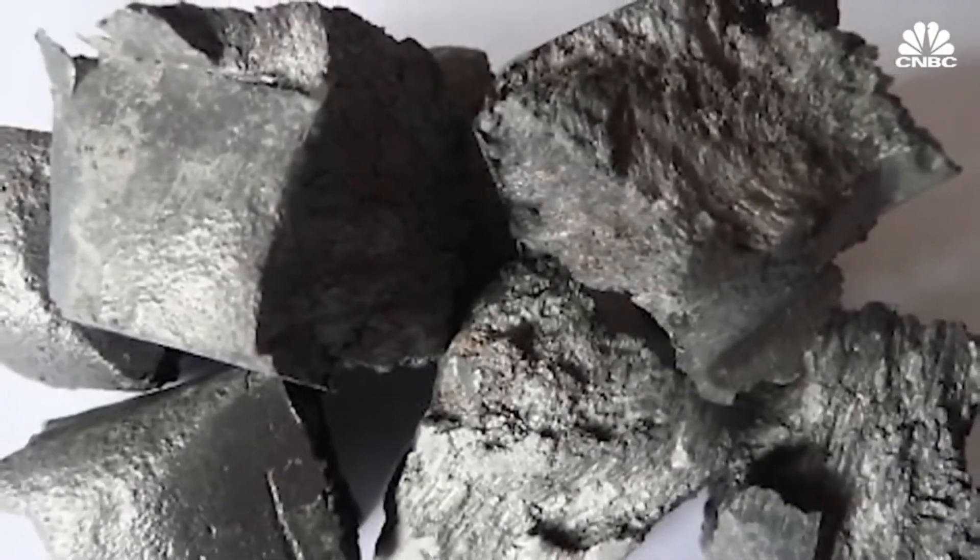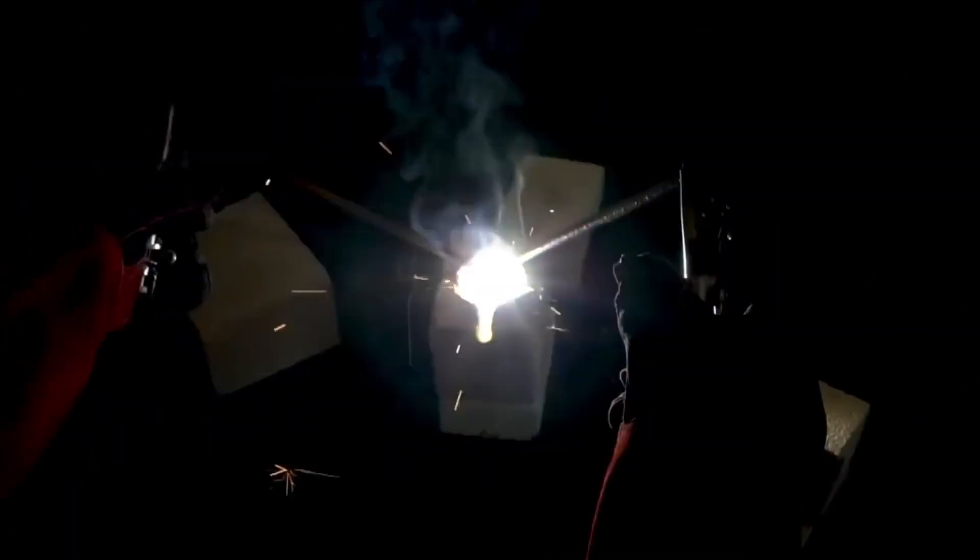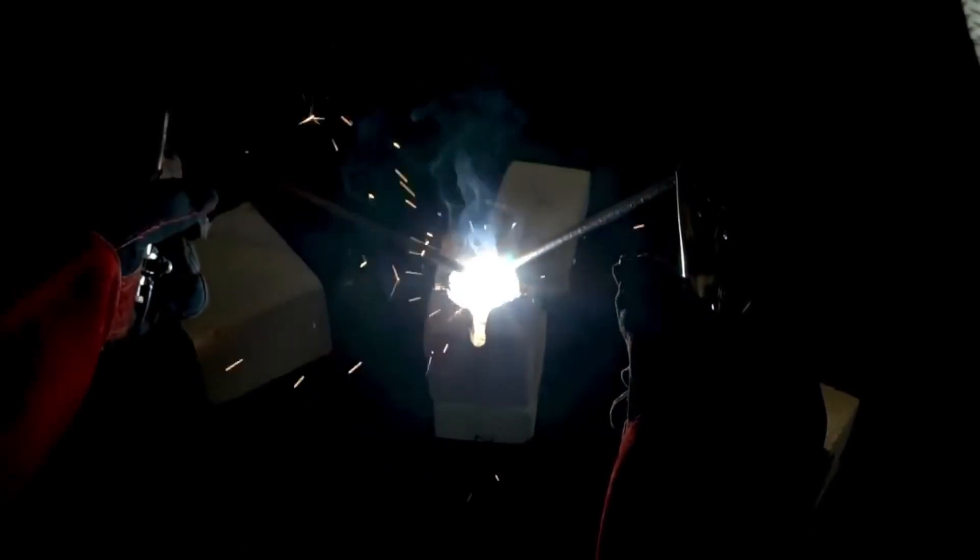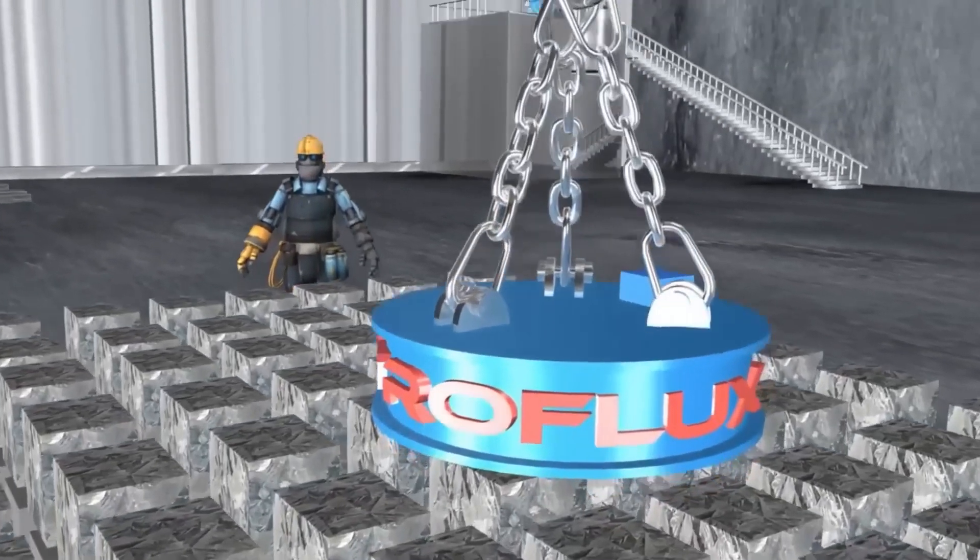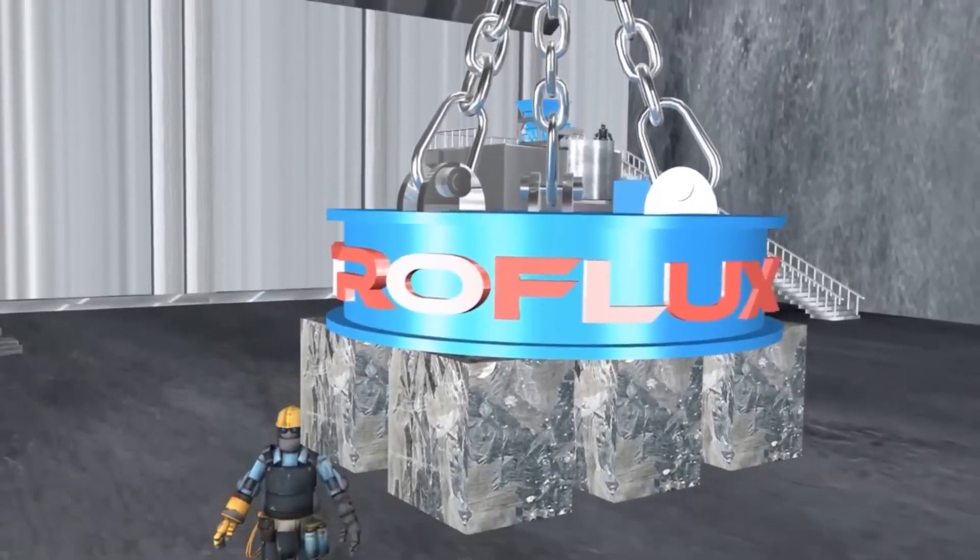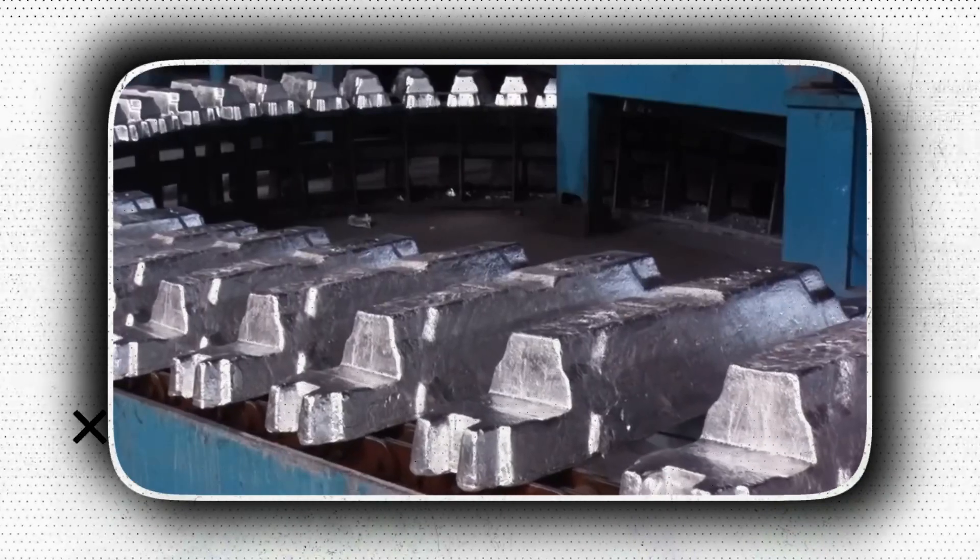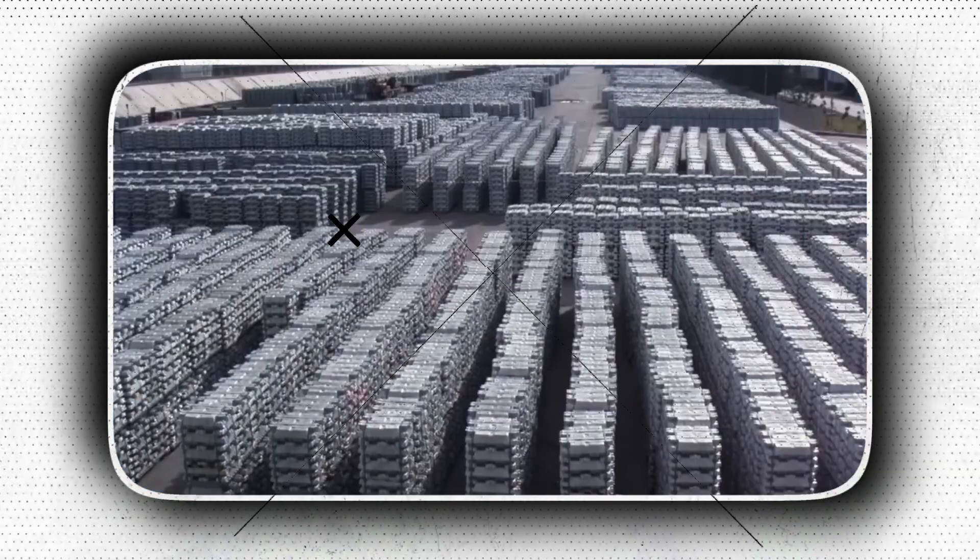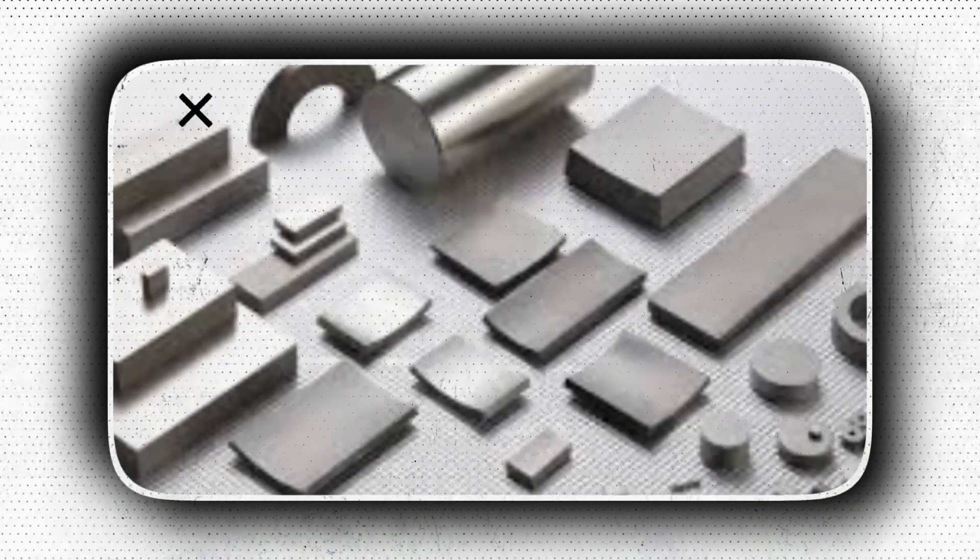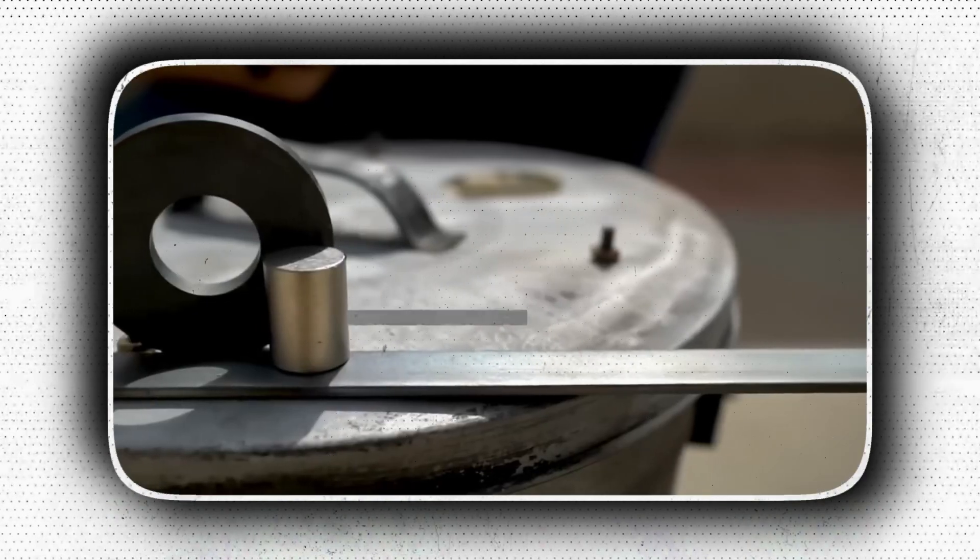Toyota has discovered an approach to lower the quantity of neodymium in electric motor magnets by 20%, with the potential to reduce it by up to 50%, while retaining the heat-resistant properties that have made the metals so popular. The grain surface of the magnets has been totally rebuilt, and the automaker has gone to a two-layer structure that places concentrated neodymium on the surface but a diluted form of the element in the core, alloying it within in a three-to-one ratio with cerium and lanthanum.